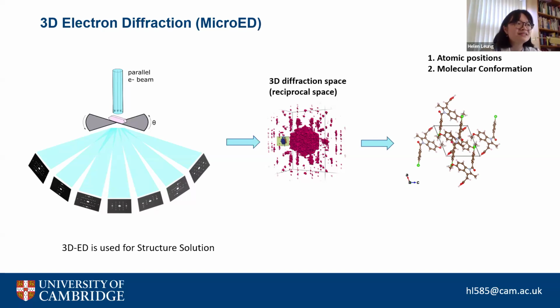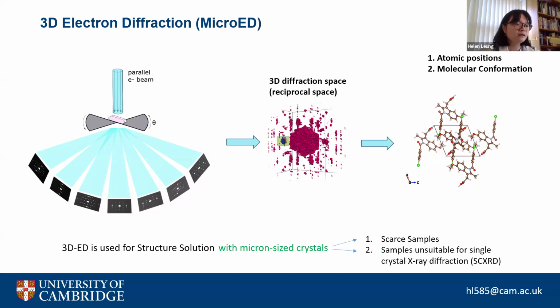And the reason why this is particularly interesting is the size of the crystals that you can have access to, which are micron-sized. And this is because in the electron microscope, we can focus an electron beam down into an illuminating area of maybe 1 micron or slightly larger. But so we're able now to access much smaller crystals. And so this is great because if you have very scarce samples, you don't have a lot of the sample, you are able to still do a structure solution potentially. Or if your samples are not able to grow very easily into crystals large enough that you would send to the synchrotron, for example, or just to do single crystal XRD on, this technique is quite a good way to do it with comparatively minimal sample prep.